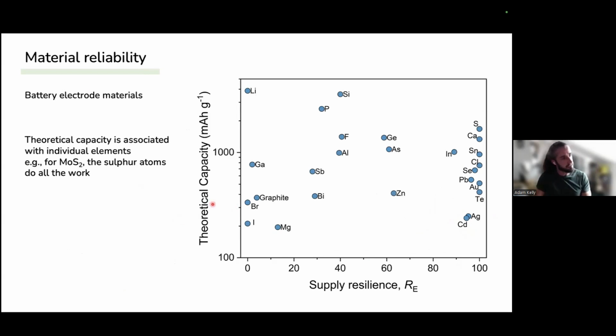individual elements, because even if you're using a compound like MoS2, the sulfur atom is doing all of the work. So molybdenum actually doesn't contribute that much. So that's why these elements here are plotted, the theoretical capacity against the supply resilience for the individual elements. So again, we see the highest resilience, the ones with the capacities like cadmium, silver, tellurium, sulfur, calcium batteries, high theoretical capacities, and we produce all of that here.